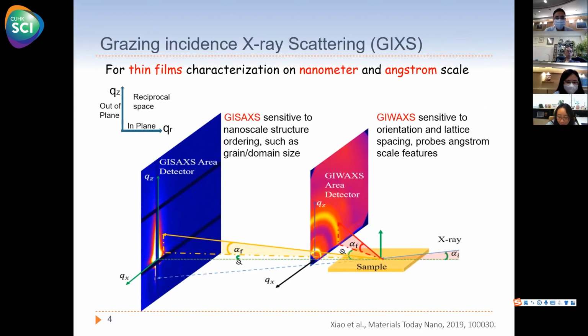In the in plane, since third generation solar cells are mostly fabricated by spin coating, it has rotational symmetry, like the jellyfish of Professor Hui. So we use this unique geometry of scattering: we impinge our X-ray onto the surface of the sample at a very tiny angle and collect the reflected scattered beam with a 2D area detector. In this way, the scattering wave vector has components in both the out of plane and in plane directions. So we can have the structural information of this thin film structure.